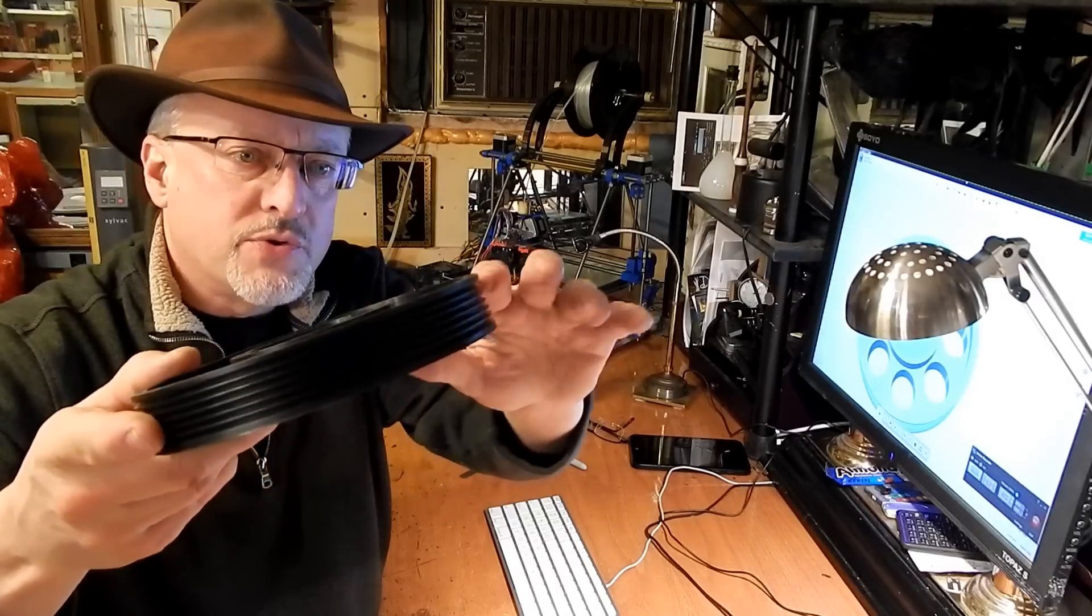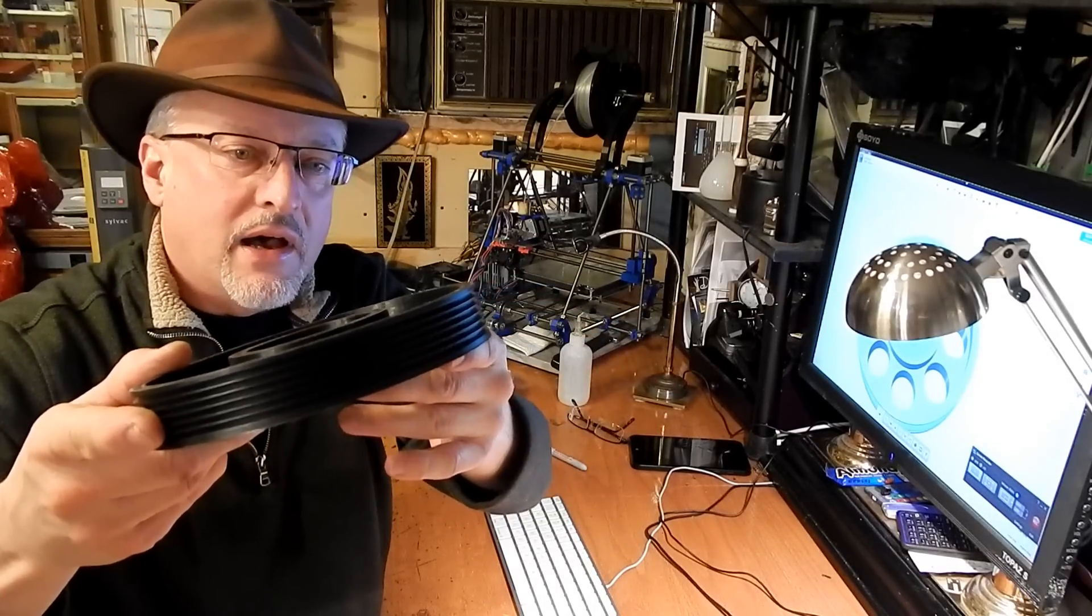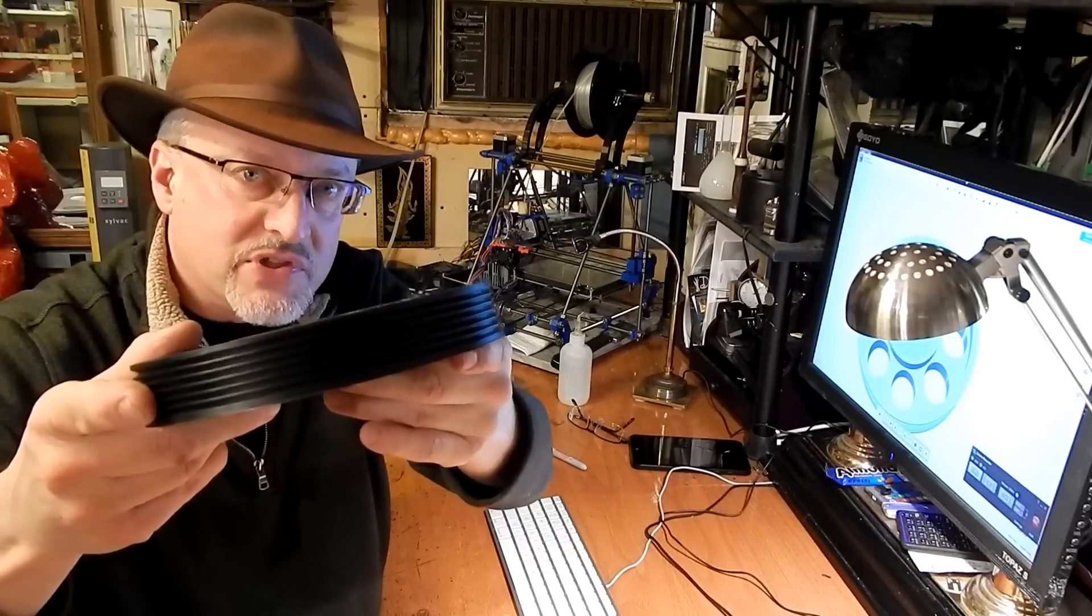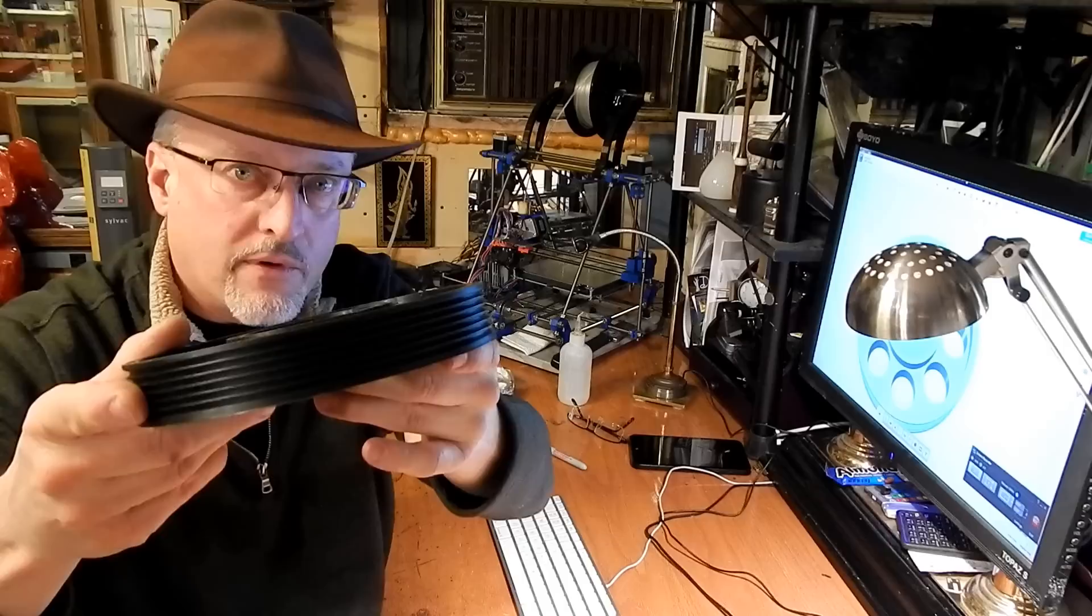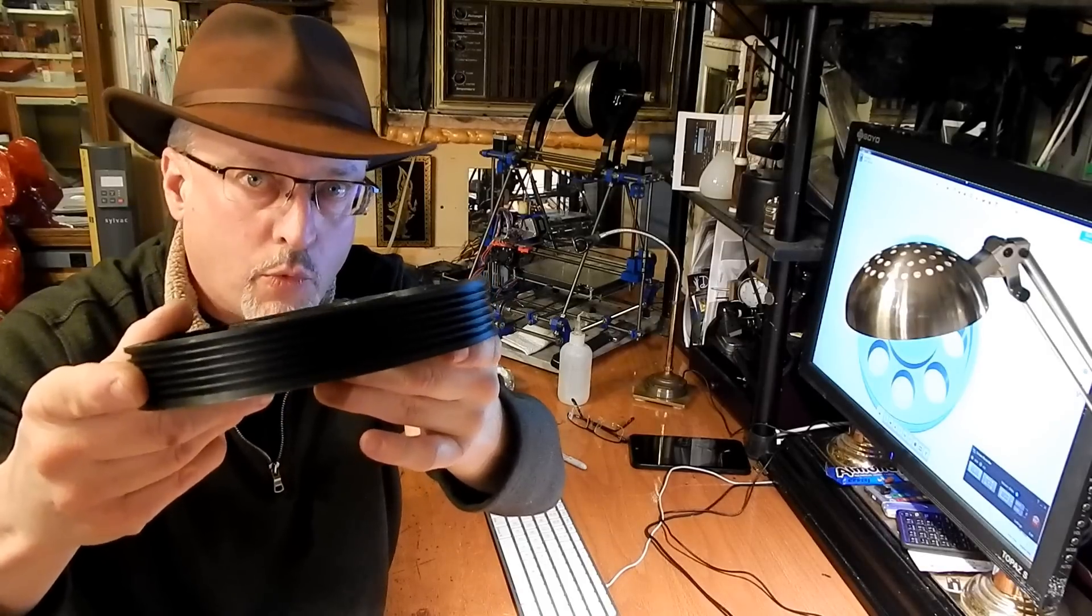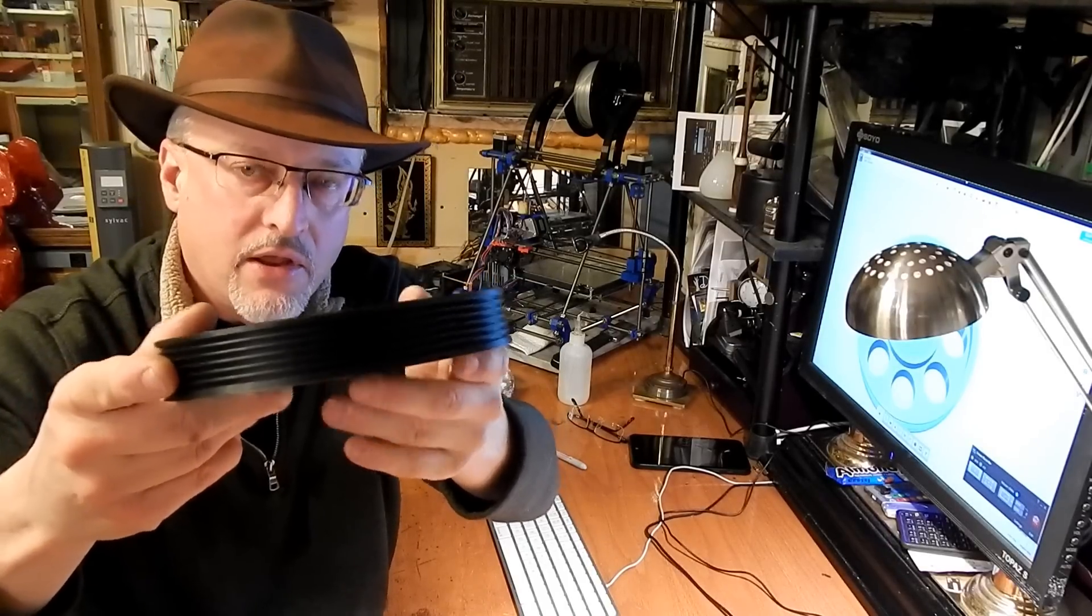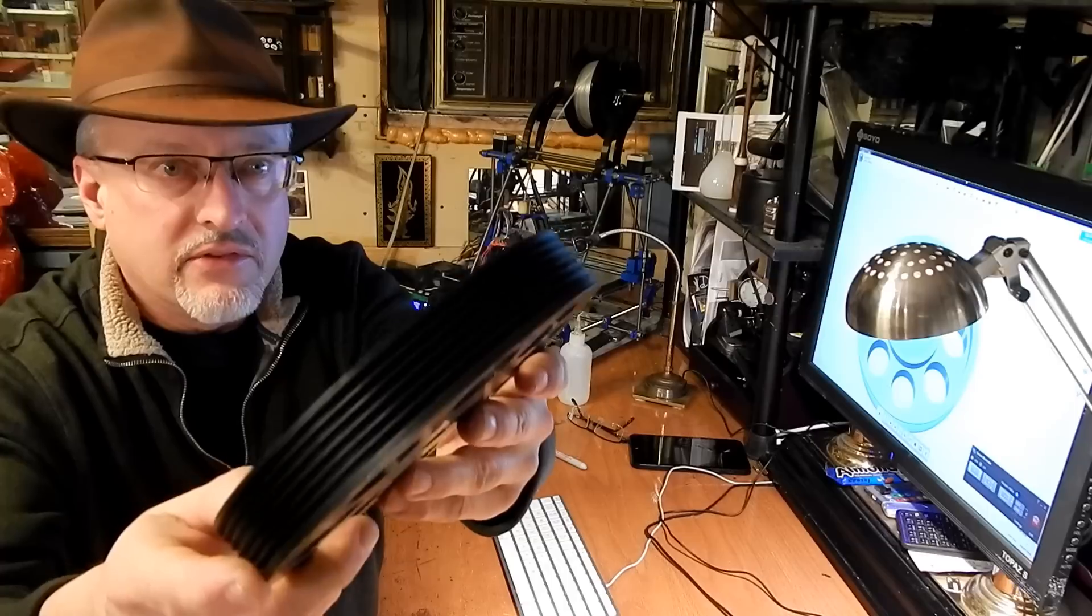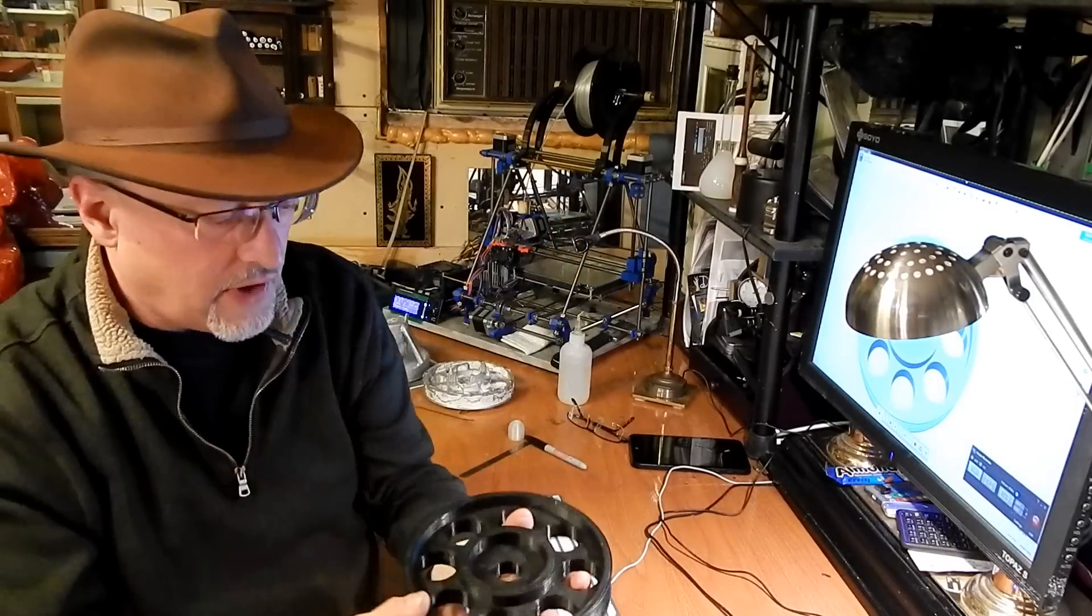So the grooves would be slightly bent over. So what I found is I had to cut my print speed down to like a half or a third of what normally would be and turn on the fan so that I would get these nice clean grooves.